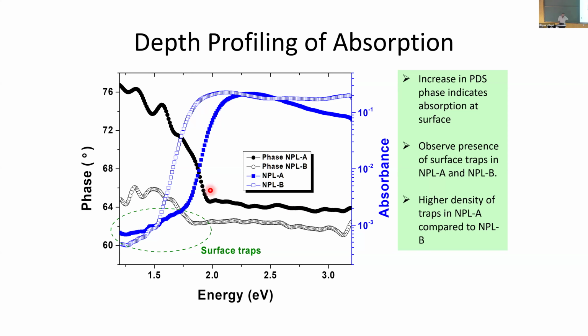So here what you see is these two samples have this absorption edge, the absorption drops, and there is remnant absorption here. This is an unwanted absorption. So I can attribute this to defects.